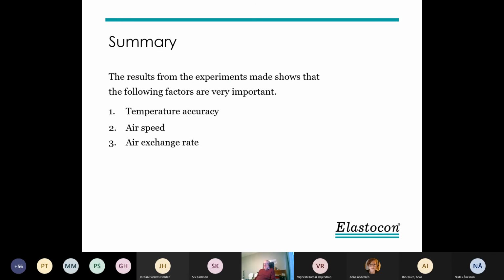So we have shown with experience that what's important is, I think, temperature is the most important thing, air speed, and then air exchange rate. But the air exchange rate seemed to be okay to be 3 times an hour. We can say that in the electrical standards for cables, they have specified 8 to 20 changes per hour, but it's not really needed. And there are standards in ASTM where they specify up to 200 changes per hour. And that is, in my opinion, just a waste of energy. We just need to keep the oxygen concentration constant and ventilate away degradation products.